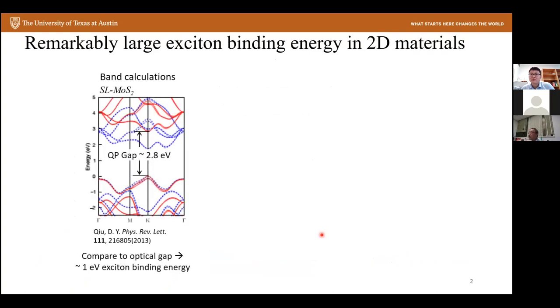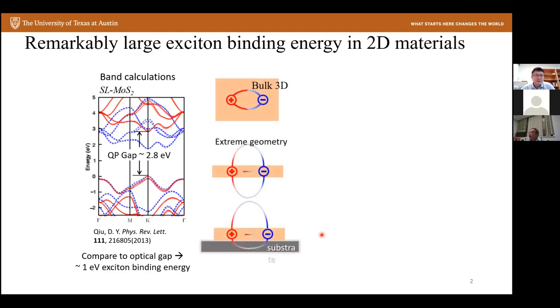Now, we got into this 2D material first by this topic. In the 2D electronic material, because of this extreme atomic geometry, the first issue that got a lot of people's attention is that theoretically there is a remarkably large exciton binding energy. This work was done by Steven Louie, the theoretical calculation in 2013, and found the quasi-particle band gap is about 1 eV larger than what people measure using the PL. And that really stimulated a lot of thinking and research activity in this area.